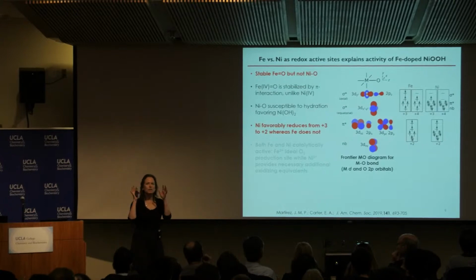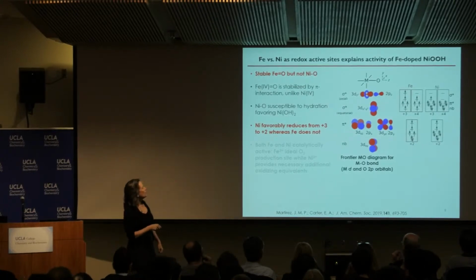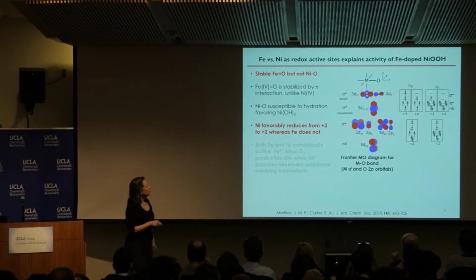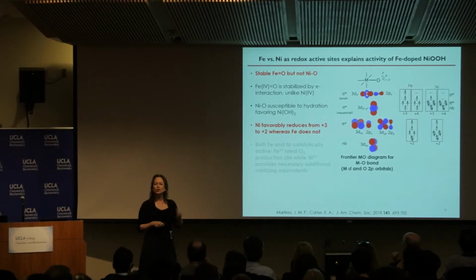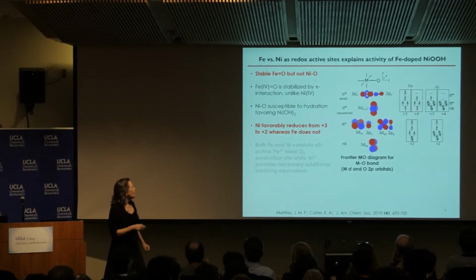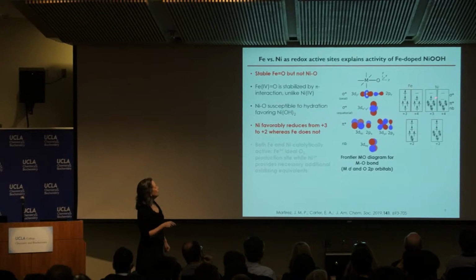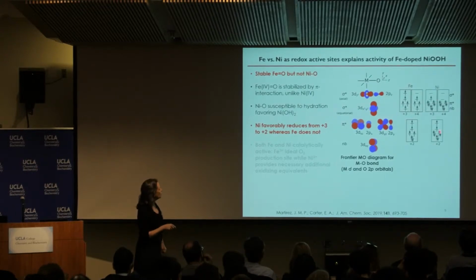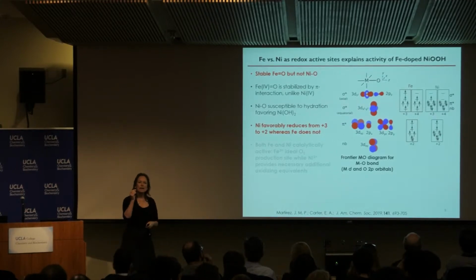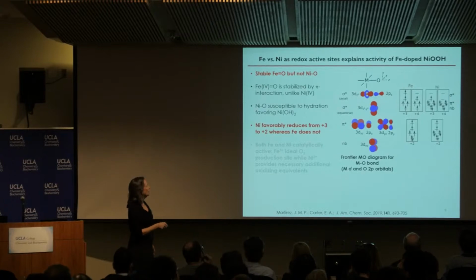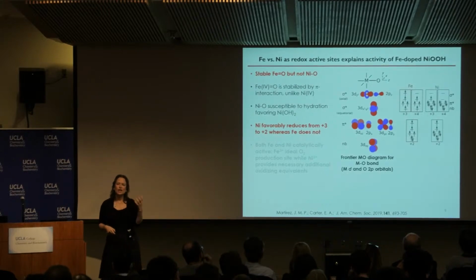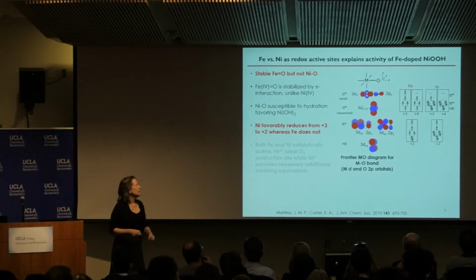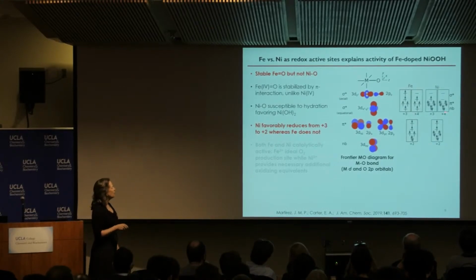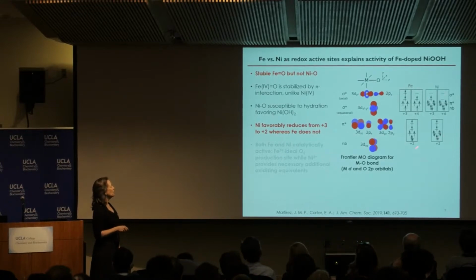Why is that? Again, fundamental insight actually from quantum mechanics. If you think about going from this high spin iron to adding a low spin electron to make iron 2, all you gain is an electron-electron repulsion by putting those two electrons in the same orbital. On the other hand, for nickel 3 plus going to nickel 2 plus, you've gone to this high spin nickel 2. Why is that good? Because you're not doubly occupying this orbital, but you also gain so-called quantum mechanical exchange interactions that lower the energy of the system by going to this high spin state. So nickel 3 to nickel 2 is extremely favorable, but iron 3 to iron 2 is not.